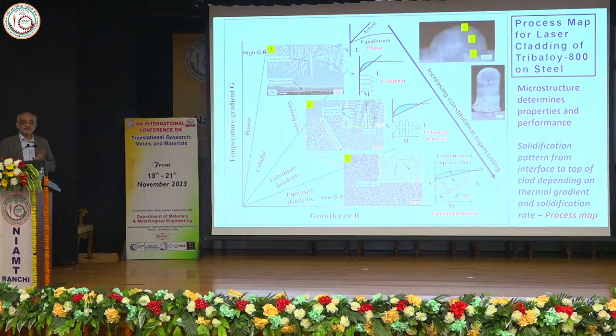Solidification behavior in large volume is primarily controlled by two independent thermodynamic parameters: the thermal gradient and the growth rate. If I plot these, it's possible even in laser processing, a small volume and very transient phenomenon, to show such microstructural mapping. With very high temperature gradient and high G over R ratio, you get directional structures. With very low G by R ratio, you can gradually change from columnar all the way to equiaxed regions. So microstructural control is also possible.